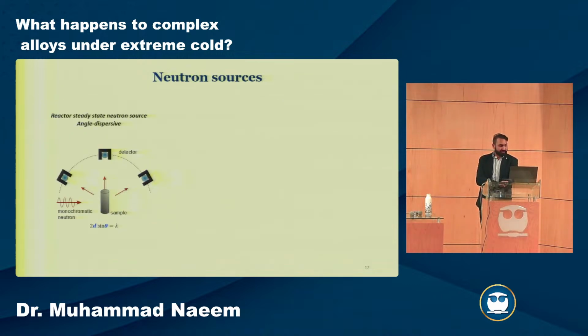Then how does it work? Here you see the reactor case, which we call angle dispersive neutron scattering. You have a neutron beam coming to the sample, and then you have detectors at different angles, and when these neutrons interact with your sample and scatter, they diffract, and they are collected in these detectors. It's quite similar to what you do with X-ray diffraction in your lab as well. The principle is the same, only the radiation is different, and it's at a much bigger scale.